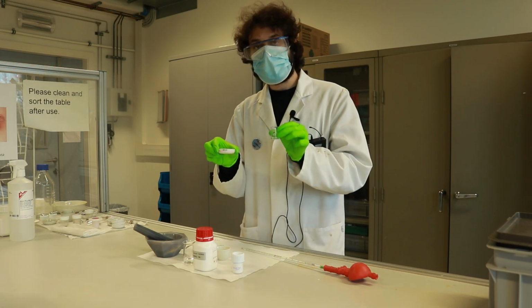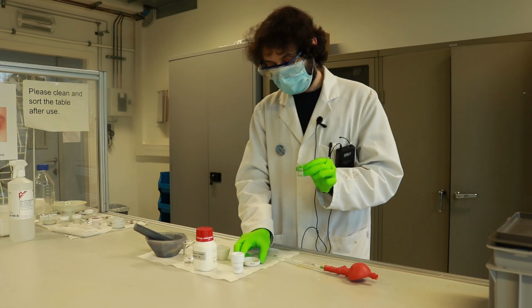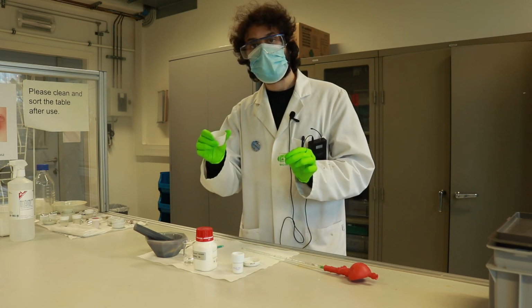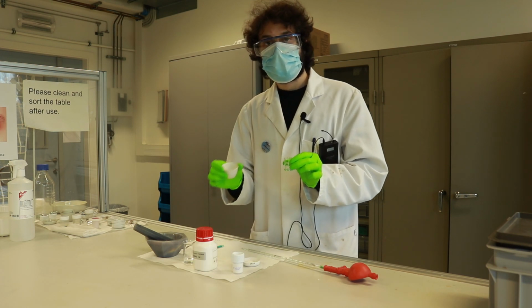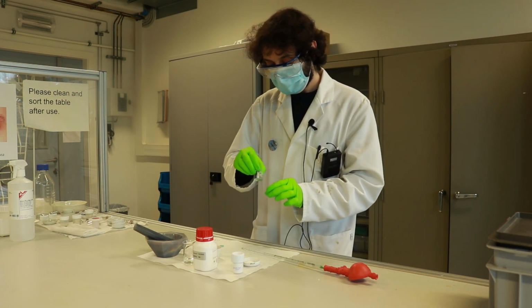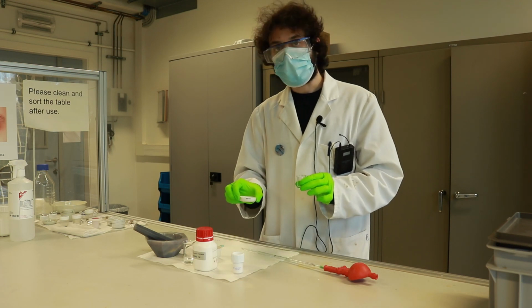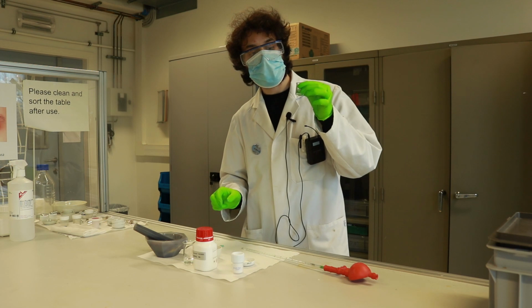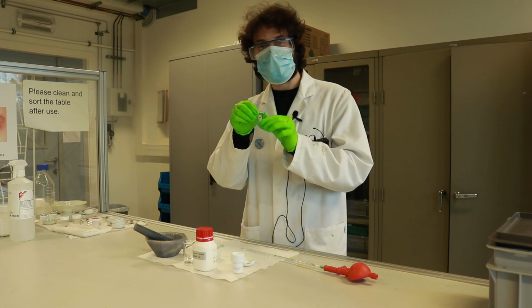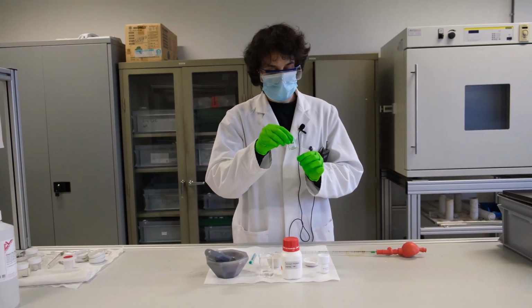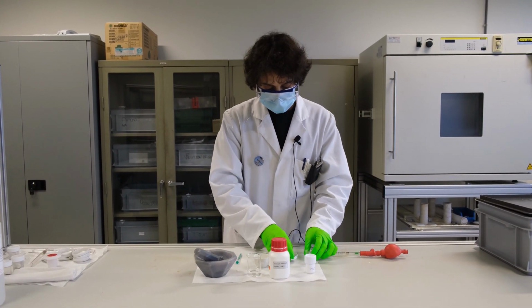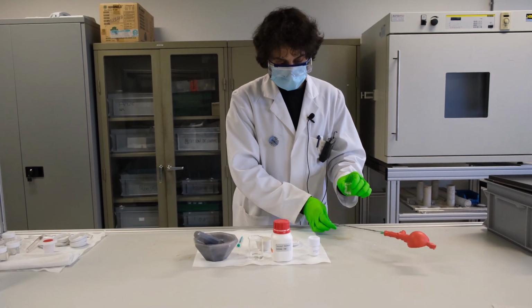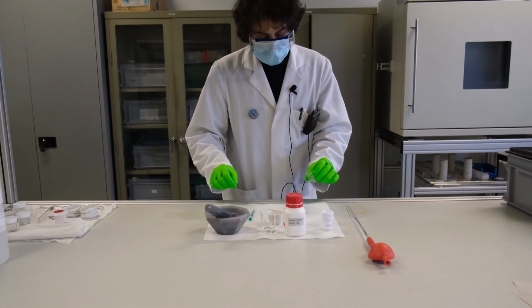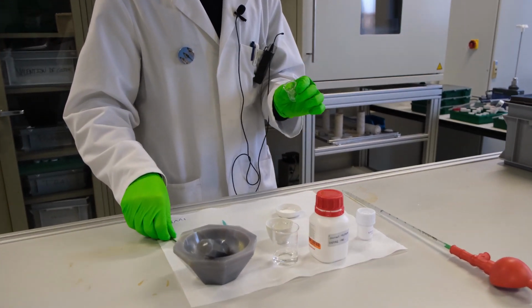And so when I mix these two together, we should end up with something very similar to what we had at the beginning when we titrated the carrier. So here I have half a gram of gamma alumina and 0.65 milliliters of a solution containing nickel. Now I will slowly add the solution to the support while mixing at the same time.